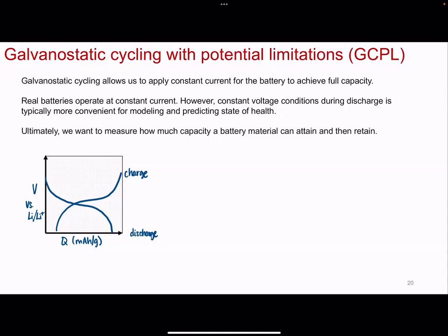When you apply a constant current to discharge, so reduce, or charge or oxidize the material, this is useful because it allows you to measure the voltage output as a function of capacity, gravimetric capacity that you can normalize by the active material that you put into the electrode, so that's fine. By time, by composition. So how much X is in the compound. So that's particularly useful.